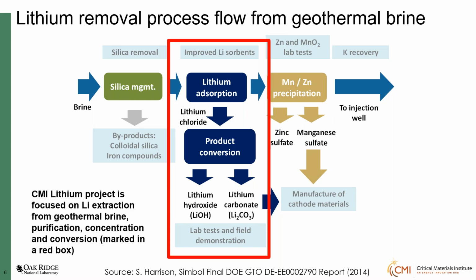So you can see, in this case, the lithium adsorption selectively extracts lithium chloride. This is happening at 95 degrees, and you get the lithium stream. Once you have the lithium stream, you can concentrate. You will get like a 3% solution. You can concentrate up to 40%, and convert lithium chloride to hydroxide, like I talked about with electrolysis, or to lithium carbonate. That's what we focused on. Other co-minerals like zinc, manganese, and potassium can be recovered, so that you can improve the economics of lithium extraction. The next slide, please.